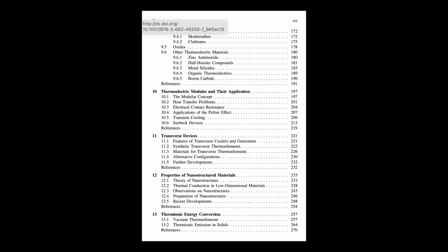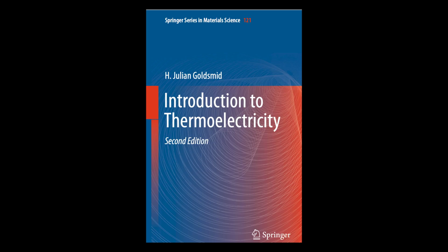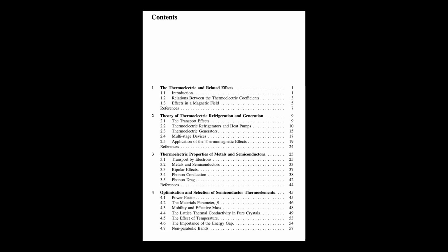A big deal then. The outline says its band structure is trickier than the simple picture. How so? Yeah, the simple models get you started, but Bi2Te3's electronic structure is actually pretty intricate. For one, the effective mass isn't constant. It changes with carrier energy and temperature. Early experiments showed results that didn't quite fit the simple theories. And there's strong evidence for a second conduction band, slightly higher in energy than the main one. These complexities affect how electrons and holes move and have to be considered for accurate modeling and optimization.